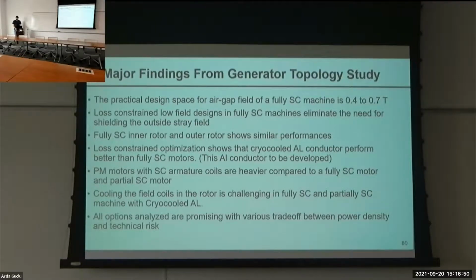So just a summary from the generator topology study is that the practical design space for the air gap is between 0.4 and 0.7 Tesla. The inner rotor and outer rotor designs for the fully superconducting machines perform similarly. The cryo-cooled aluminum machine actually performs better than the fully superconducting machines, but the aluminum conductor has yet to be developed. And the permanent magnet motor with superconducting armature coils is heavier compared to the other topologies we looked at.